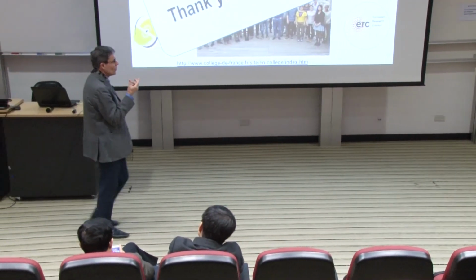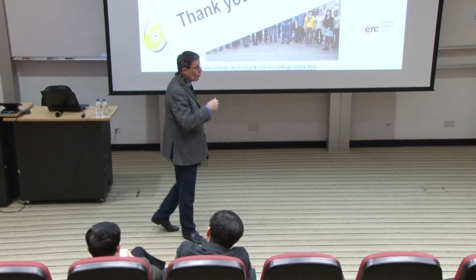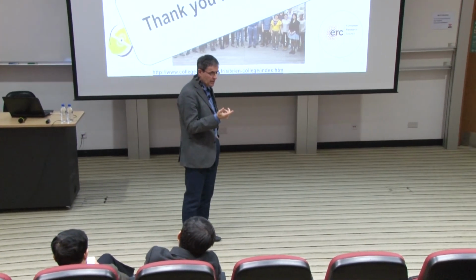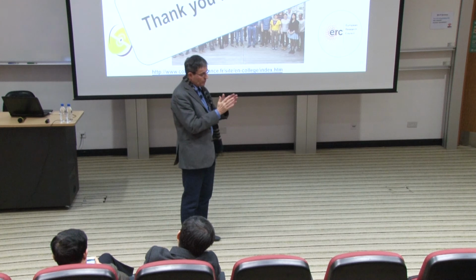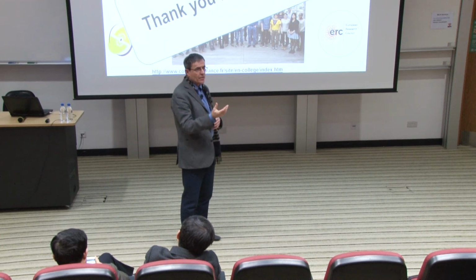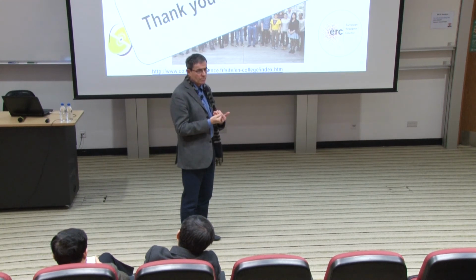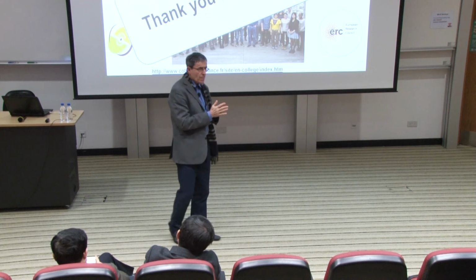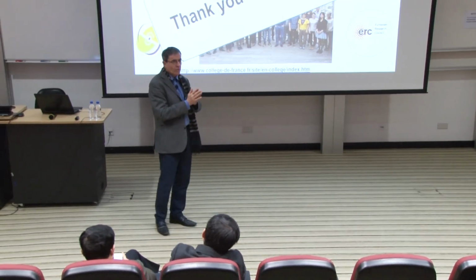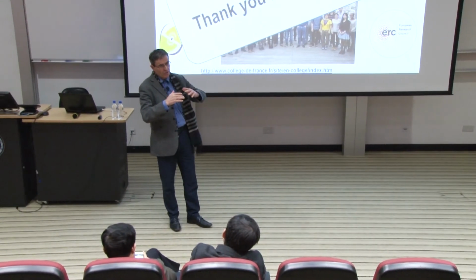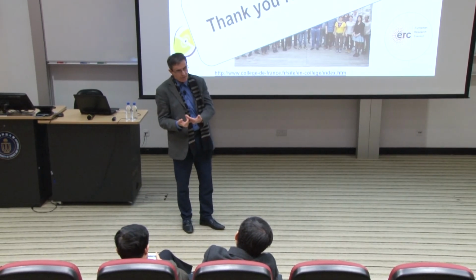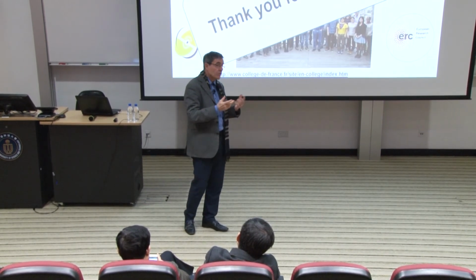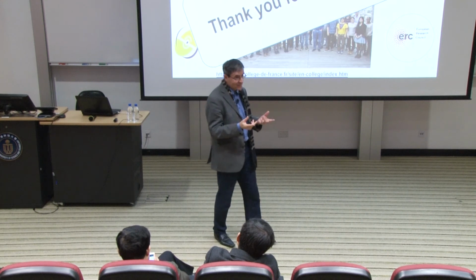When you have this kind of oxygen release, I think what is really happening is you are creating a radical. And the oxygen radical within the structure is relatively unstable. So I think the oxygen radicals try to decorrelate from the structure to recombine into oxygen gas. And what is the energy to do this, I don't know.